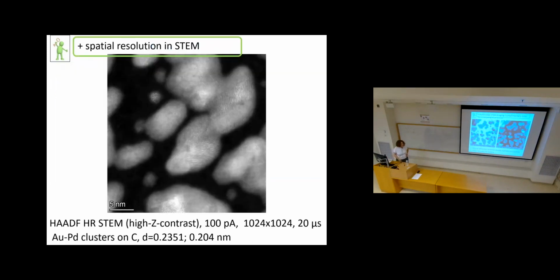And here is the example of the complementary data. Here and here, we see the same sample. So gold palladium clusters on carbon are here, acquired with high annular dark field. And what do we see here, in addition to the atomic resolution in the gold palladium lattice? We see the contrast which is called high Z contrast, because we have extremely heavy clusters of gold, extremely heavy because gold is number 79 and palladium is number 46. And the contrast in this image is roughly proportional to the square of Z. And the dark regions we have here are from carbon, because carbon is only number 6.